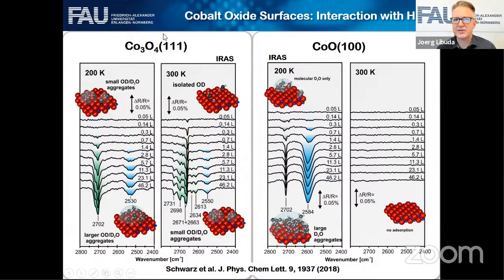Now we take this surface that is terminated by the same ions. Now we expose it to a little bit of water and hell breaks loose. So a little bit of water makes OH groups on the surface. Immediately the water dissociates. Then we put more water and we get a very complex infrared spectrum. All kinds of well-defined structures assemble on the surface. And we have shown that these structures consist of OH groups, dissociated water molecules, and molecular waters assembled in a certain way. So very strong interaction.